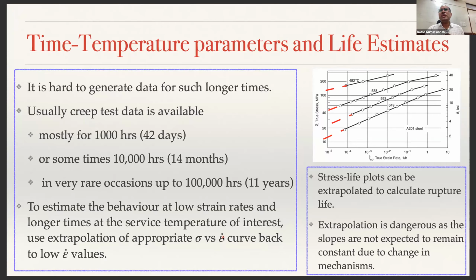So, usually creep test data is available mostly for 1000 hours. If you look at this, this is the true stress and steady state creep strain rate at a temperature of 482 degrees Celsius. This data is usually available for 1000 hours, or at most sometimes 10,000 hours, and on very rare occasions up to 100,000 hours. 100,000 hours is about 11 years. Most of the creep data is available for 42 days. One creep experiment will take a minimum of 42 days.